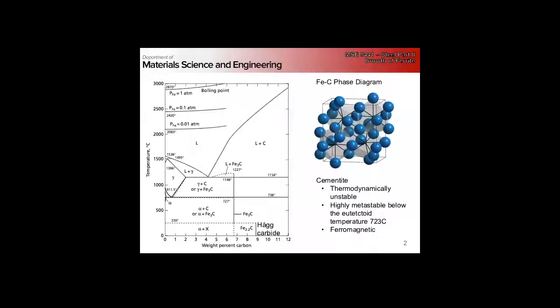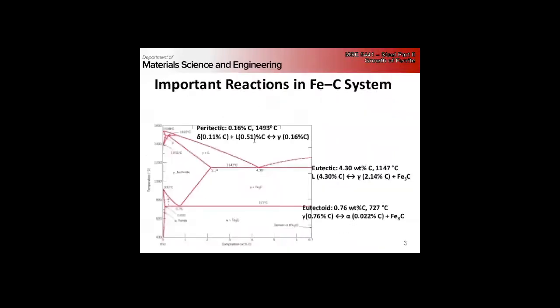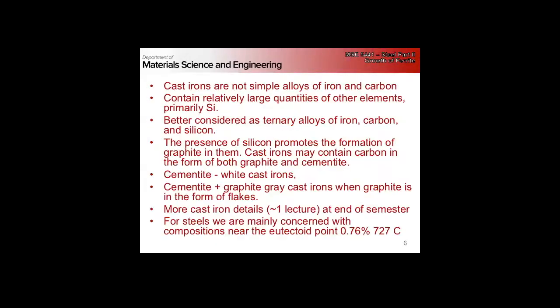Okay, so we started looking a little more carefully at the equilibrium or metastable iron carbide phase diagram, and we pointed out that for the most part we're going to be concerned with the formation of ferrite and cementite and how this happens, but there's other carbides that can come up, such as the Hagg carbide. We identified important reactions in the system, and we said that the peritectic reaction doesn't have too much of an effect, but really we're mostly concerned about things happening near the eutectoid region.